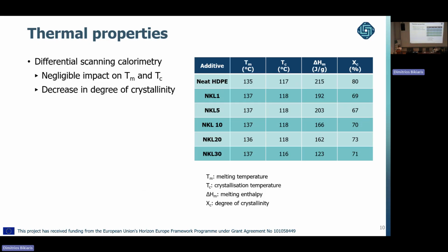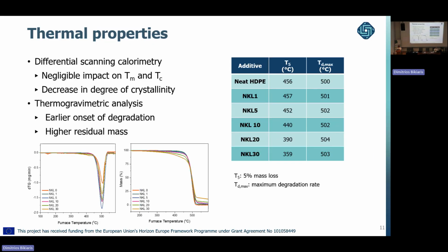Thermal properties were studied through differential scanning calorimetry. So we can see we have a negligible impact on melting and crystallization temperatures, and we have a decrease in the degree of crystallinity. And when it comes to the thermal stability of the composites, we have an earlier degradation. The temperature of maximum degradation rate is approximately constant, and we can see we have a larger residual mass at 600 degrees.